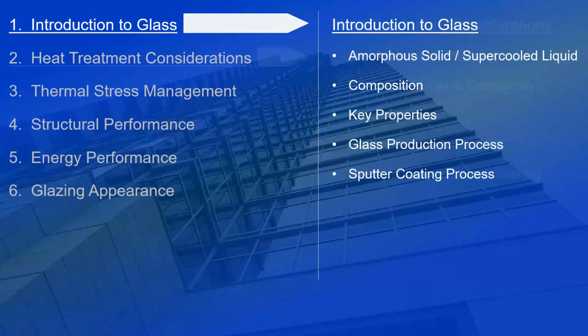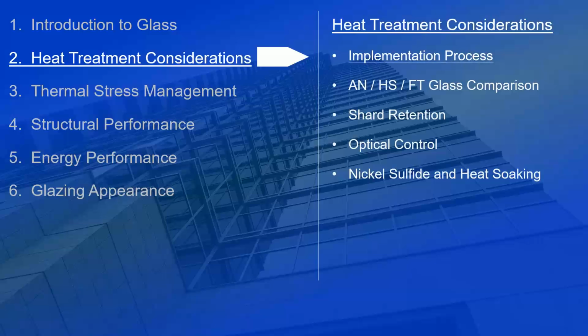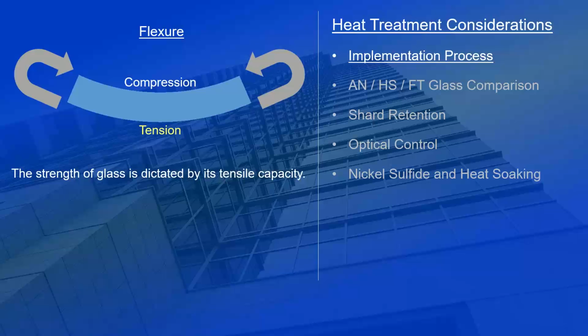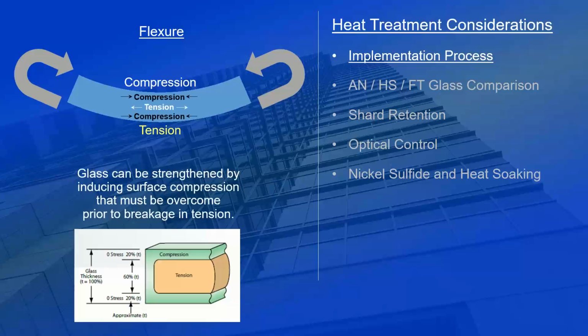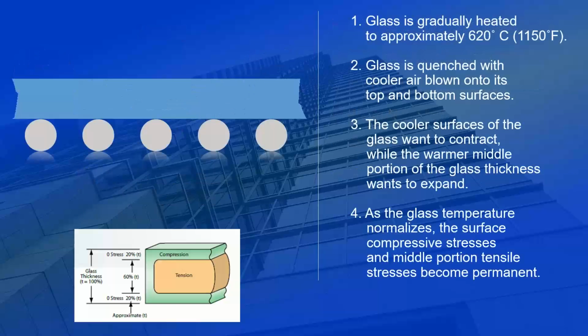So we talked about glass Low-E coatings. Let's look at heat treatment considerations for a moment. What is the process for heat treatment, and why is heat treatment done? So the strength of glass is dictated by its tensile capacity. If we look at a cut through of a glass light, when the glass gets heat treated, the idea is that we are putting the outside layer, the perimeter of the glass, in compression, by having that perimeter be cooled quicker, and then the inside of the glass is put into tension because the inside cools a little bit slower. So let's look at that for a moment.